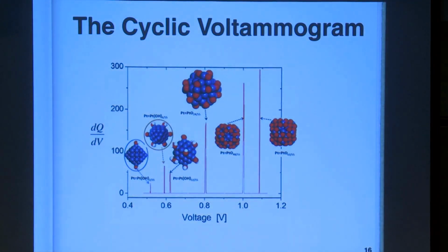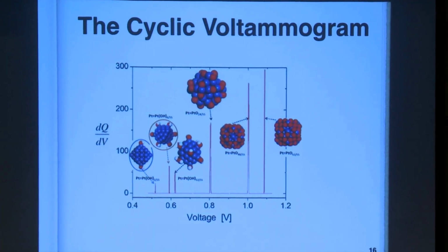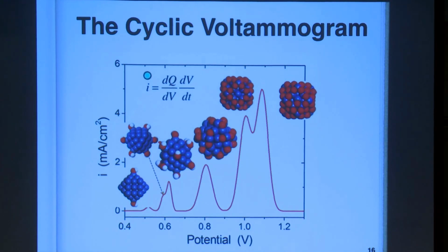How about electrochemical properties? First-principles calculations can even predict cyclic voltammograms on the basis of a completely pure first-principles database. Here, you know exactly the structure, and we know how much proton and electron has to transfer to form these structures. If you apply this theory, current density and the time variation of voltage, you can find the peaks. Whenever there is an electrochemical reaction, you can see a peak like that. Then you can give this data to experimental measurement, and you can validate the database.